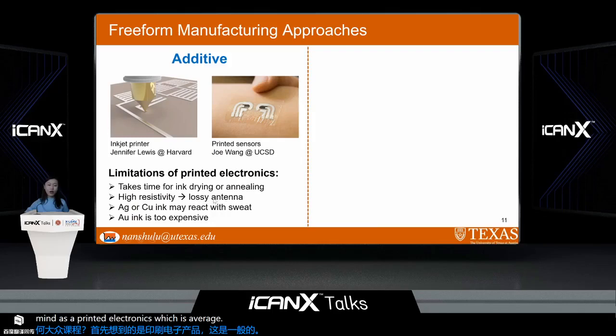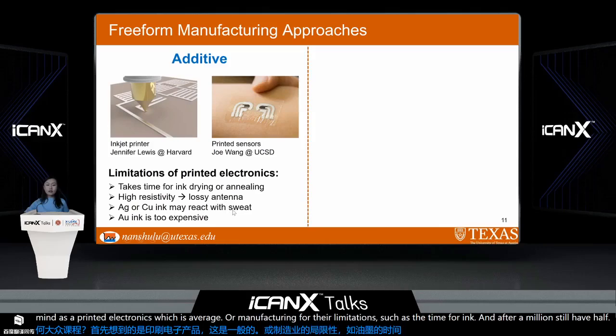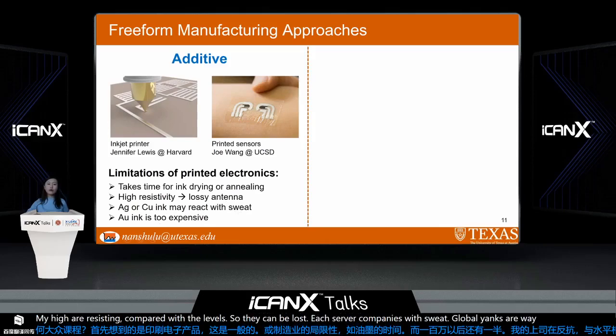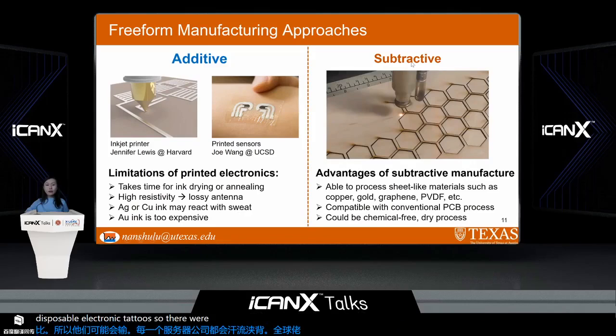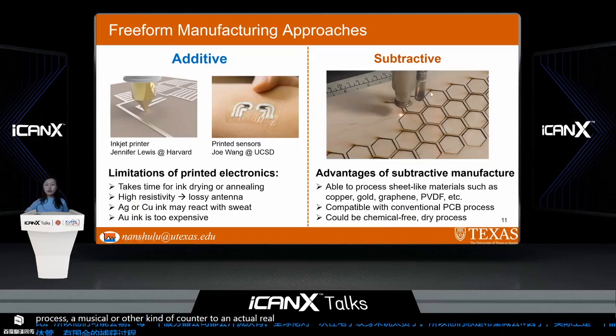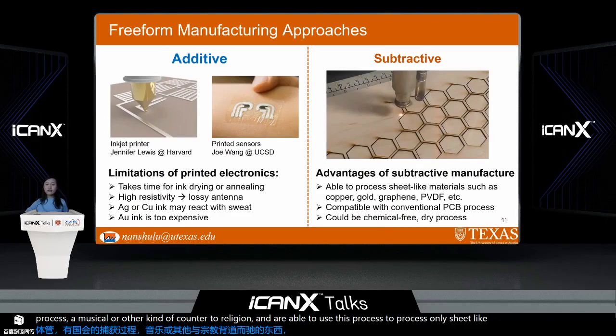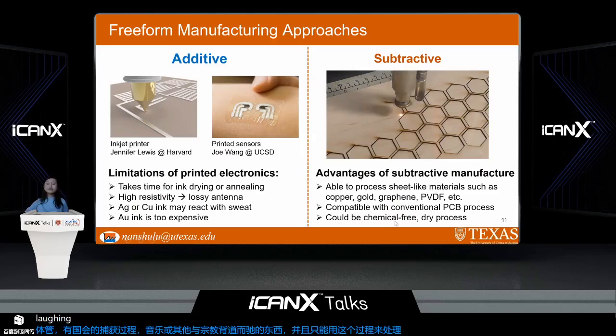And the silver or copper inks are easy to oxidize and react with sweat. Gold inks are way too expensive for disposable electronic tattoo use. So therefore, we started to look into subtractive manufacturing, which is actually consistent with the conventional PCB manufacturing process. We use a mechanical or laser cutter plotter to selectively remove the region. And we are able to use this process to process already sheet-like thin films, such as copper, gold, graphene, or even piezoelectric materials. And it is also a completely dry process.